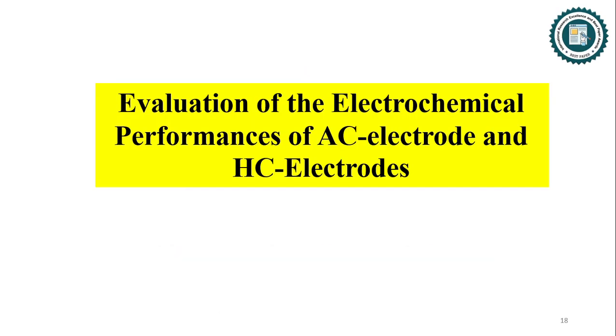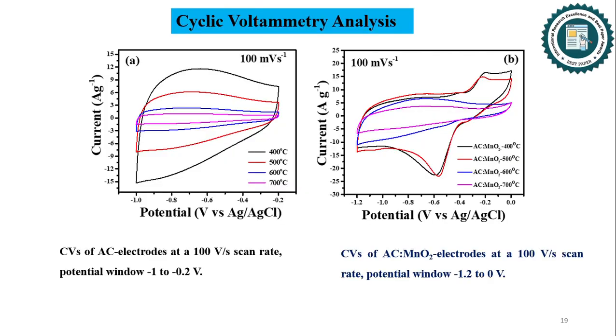Now I'm moving on to the evaluation of electrochemical performances of the AC electrode and hybrid composite electrodes. I'll start with cyclic voltammetry analysis. This slide shows cyclic voltammograms of as-fabricated activated carbon electrodes and hybrid composite electrodes incorporating manganese dioxide at various carbonization temperatures. Cyclic voltammetric analysis of activated carbon electrodes exhibited robust electrical double layer capacitive behavior, that is EDLC behavior with high specific capacitance, while hybrid composite electrodes showed enhanced charge storage due to combined EDLC and pseudocapacitive contributions.